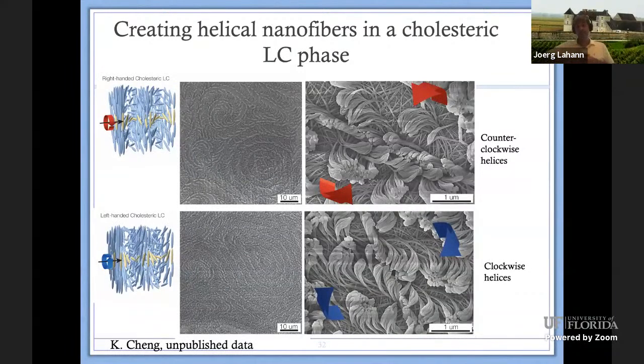So this is cholesteric LC, but this time we're comparing a left-handed and right-handed cholesteric LC. So basically the dopant has opposite chirality in both cases, and you can really see how that then impacts the swirling direction of the nanofibers here. So we can essentially then create counterclockwise or clockwise helices with this process.